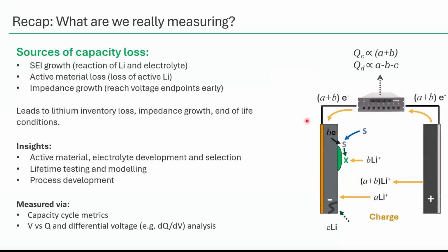I think everyone's fairly familiar with capacity loss. These are things like SEI growth, active material loss, impedance growth, that as we're moving lithium across in the cell, we're counting these electrons. We lose some of these due to these failure mechanisms, due to electrolyte reacting at the anode material, or active material loss or cracking happening at either electrode. And cycle to cycle, we end up losing some capacity here.